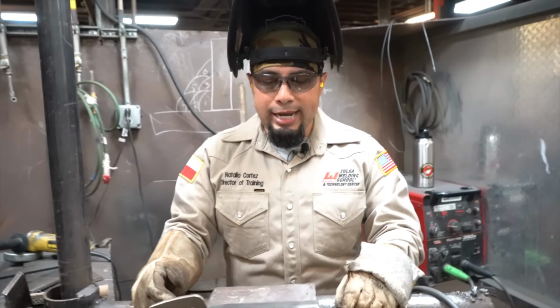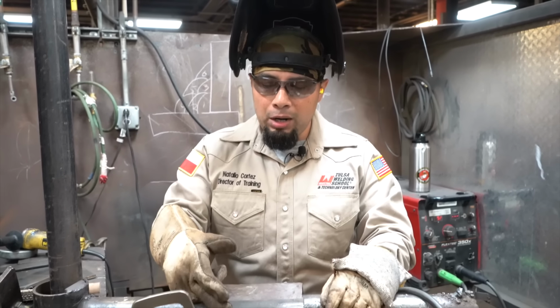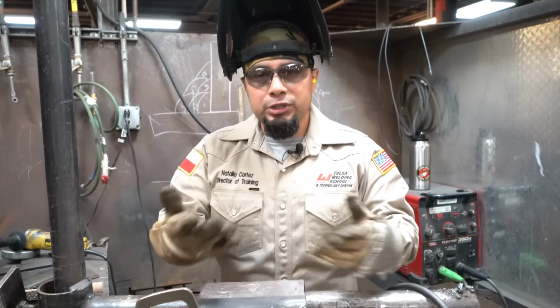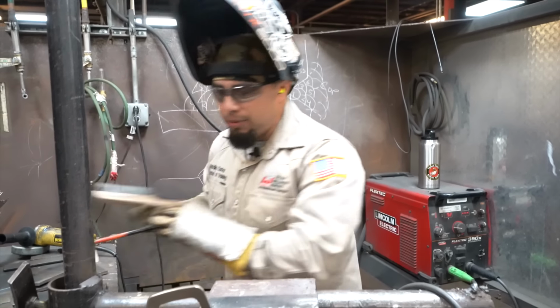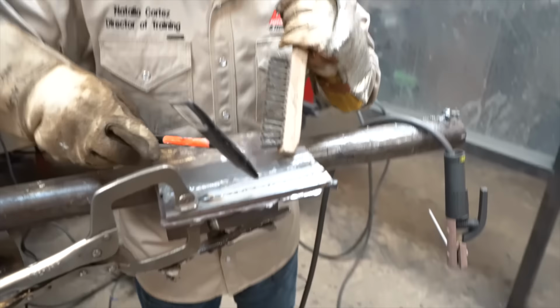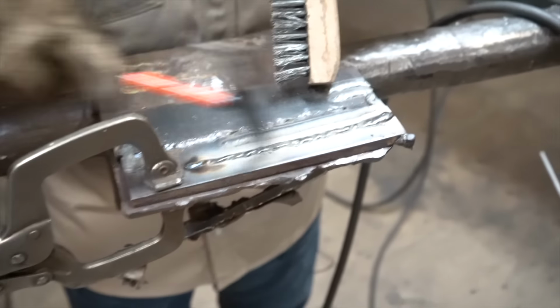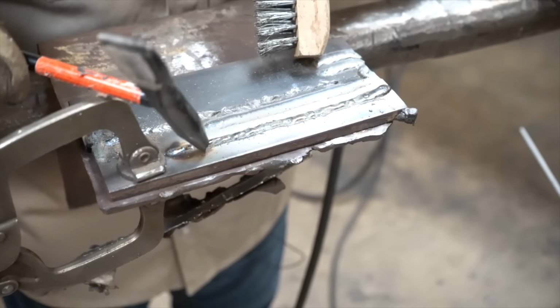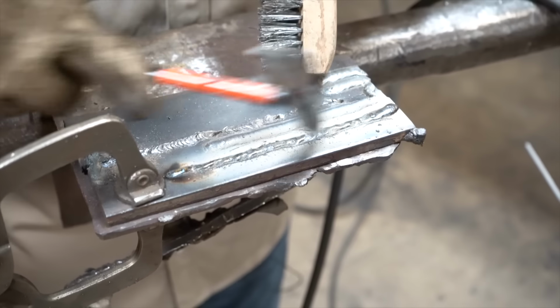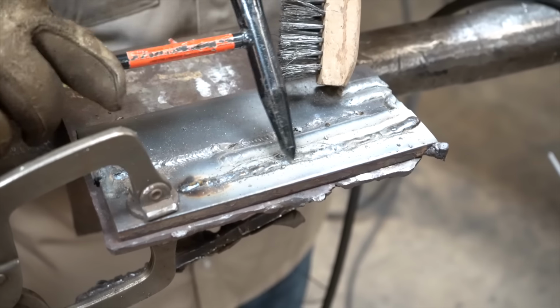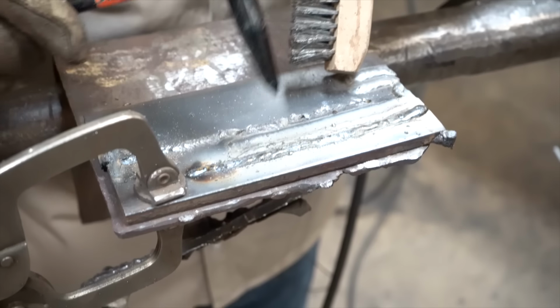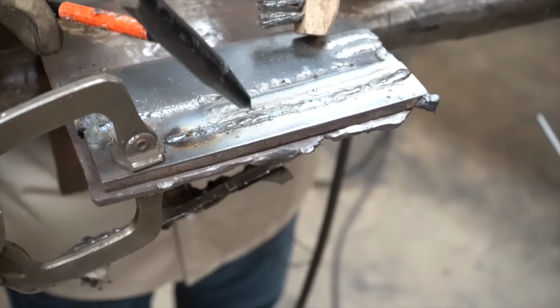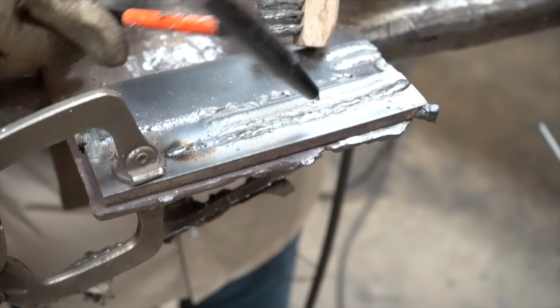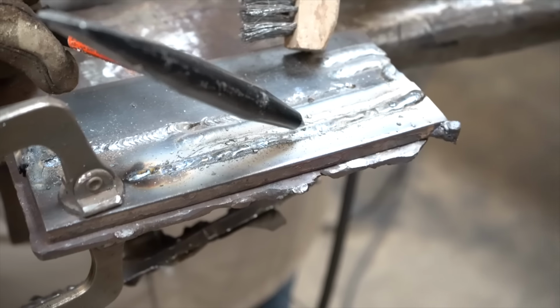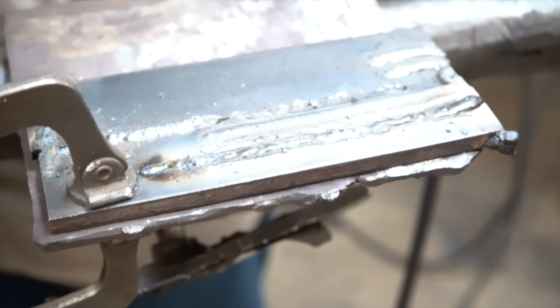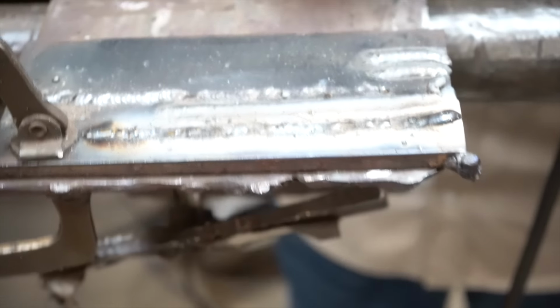So we just finished running a weld. We ran a proper weld and a dragging weld, which is too fast. Even cleaning it up makes the weld more difficult to clean off. With the chipping hammer, if I try to knock off that slag, because I went too fast, it's going to be that much harder to chip away at the slag. You see that? So now, in this case, I'm going to have to chip at it, which I don't want to do because that might add a defect to my weld. All right? So I'm going to use my wire brush to help me clean this off, or my wire wheel.